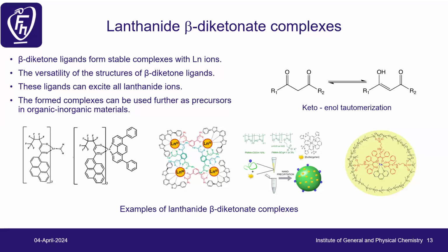Lanthanide beta-diketonates. What are beta-diketonates? Those are small, quite simple ligands, where we have two oxygen keto groups next to one another. And in the free form, they also have this keto-enol tautomerization, so they can go from keto to enol. And here, the carbon beta hydrogens in this one can be quite easily extracted because they have a quite low pKa, and then we can have our complexes.